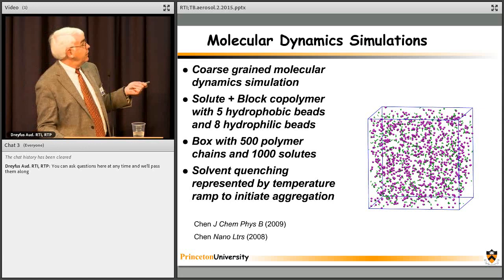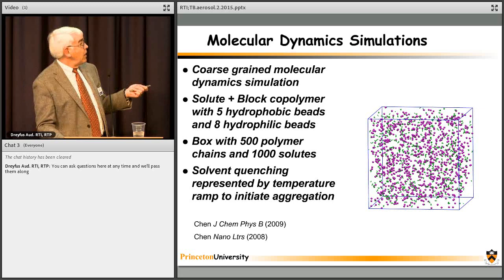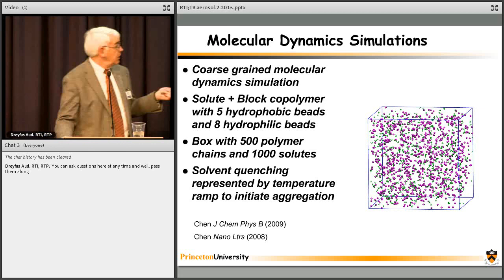The solute and block copolymer are simulated with 5 hydrophobic beads and 8 hydrophilic beads. The box has 500 polymer chains and 1,000 solute molecules. And then the solvent quenching is represented by temperature quenching to initiate aggregation in the simulation. And here are the two papers where this appeared.